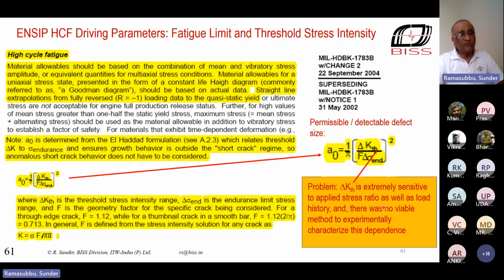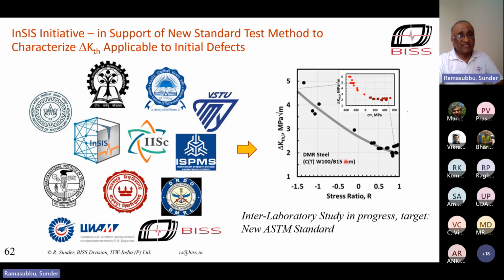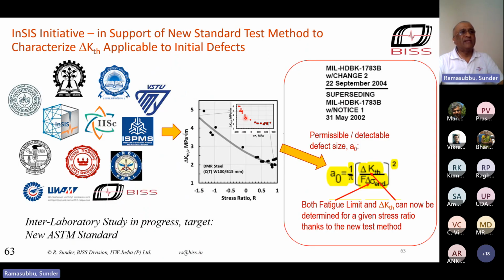And I'm delighted to share with you today, some of you who may not be aware, that INSIS is carrying out an interlaboratory study right now, and we hope to finish it this year, to come up with a new testing practice, new test method that characterizes threshold stress intensity as a function of applied stress ratio. We have results already on a DMR steel, which we got from DMRL, and a number of Indian institutions have got together along with colleagues in Russia. And we hope to come out with results that will convince the American Society for Testing and Materials to adopt this new method as standard practice. So we hope to have a made in India test method that will be used globally, and that will have a huge impact on the determination of permissible detectable defect size.